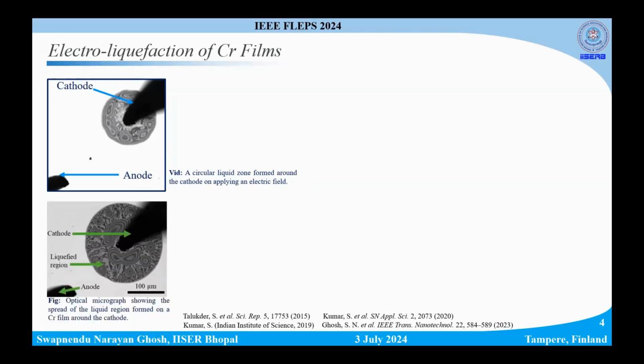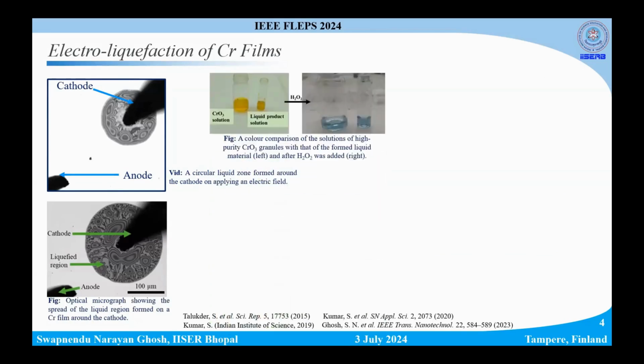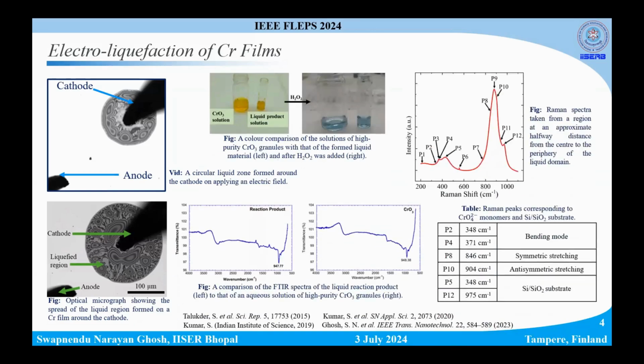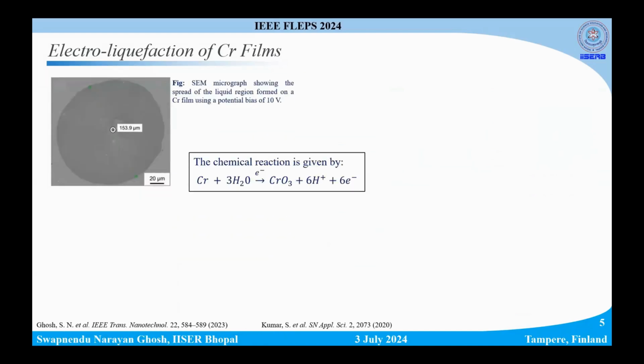So, what happens if we take a chromium thin film and electrically stress it with a pair of probes? Around the cathode, we see that a liquid material starts to form, which spreads radially outwards, and can spread to 100 microns in radius or even to 200 microns. We did a lot of material characterization, including wet tests, FTIR, and Raman, to find out that this material that is formed is basically the hydrous form of chromium trioxide. This is one SEM image.